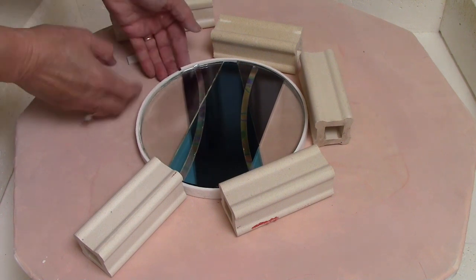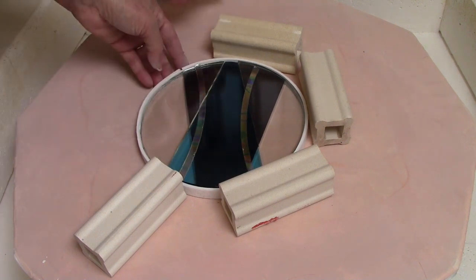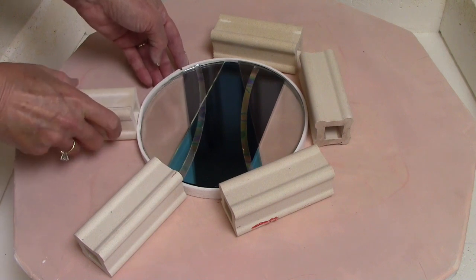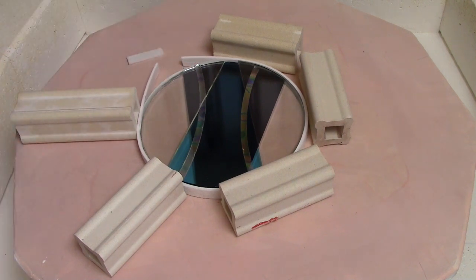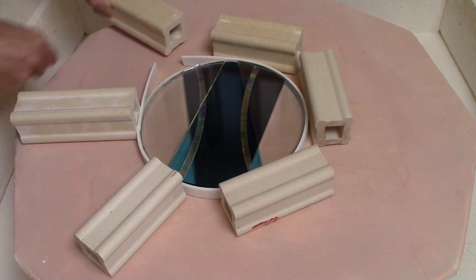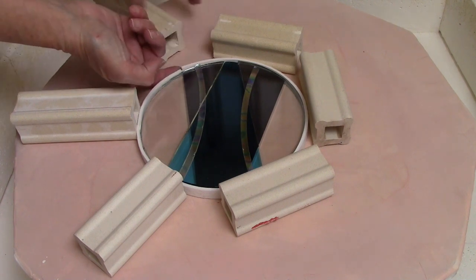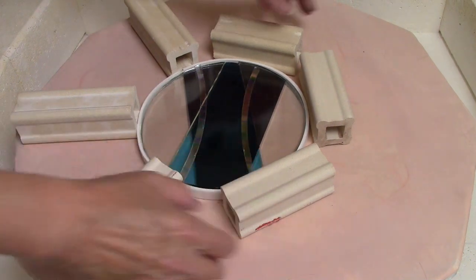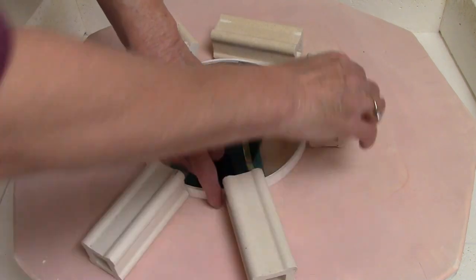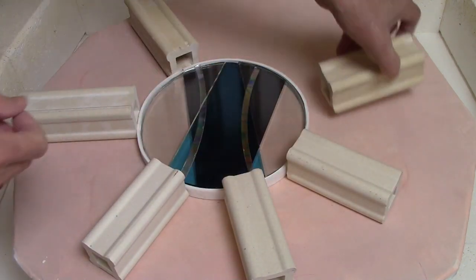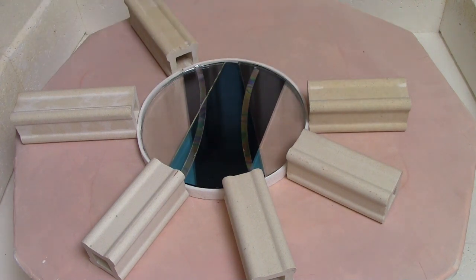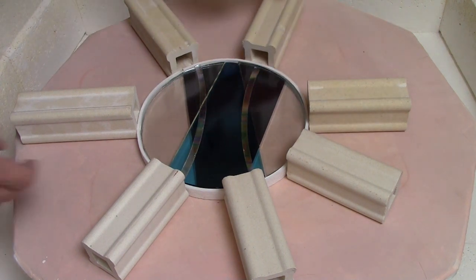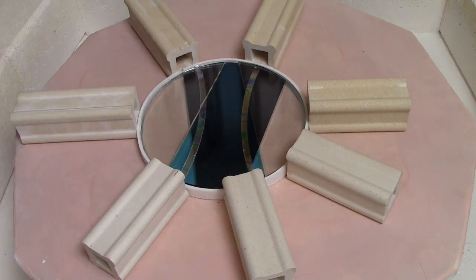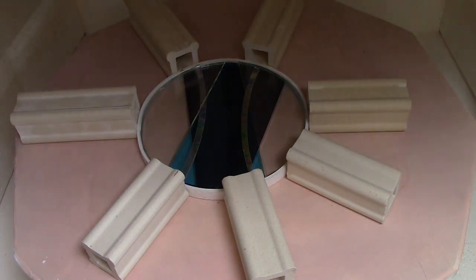The reason we need the glass really thick is that when we place this glass on top of a dropout mold, it's a ceramic mold with the center missing. We prop that mold up on kiln posts, and then we have this glass drop through the center of that donut hole. When that happens, the glass stretches and pulls, and it becomes much, much thinner. So you have to start with a really thick blank in order to have a decent thickness in the finished vase. The vase comes out really delicate and elegant. It's really a beautiful style, but the construction seems a little strange that you have to start so thick.